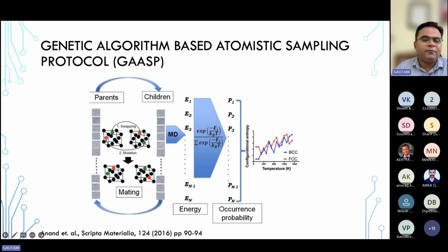What it does is, first of all, you generate some random structures for an alloy of your interest, say aluminum, cobalt, chromium, iron, nickel. From there, you take some low energy structures and use this genetic algorithm-based atomistic sampling protocol to generate newer alloys, so parent to children. Once you have done that, you carry out molecular dynamics using a classical interatomic potential. For those who don't know, you can calculate the energy of an ensemble of atoms by quantum mechanics, which is very accurate but very expensive. So you can also use fitted interatomic potentials, which can be fitted by machine learning based methods, or earlier people were just fitting them empirically to come up with some rules of interaction between atoms.